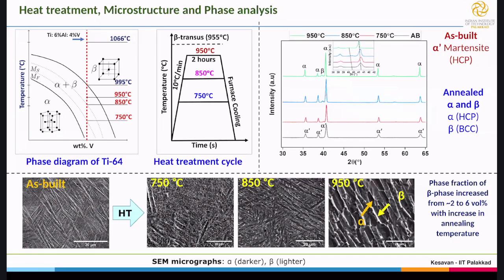So the remedy or mitigation is that I have to take it for heat treatment. Why heat treatment? I need to restore the desirable phases or structures. So I take the material and heat it close to the beta transus temperature, which is almost 955 degrees Celsius, and do furnace cooling. Here we kept it at three different temperatures close to the beta transus, namely 750, 850, and 950 degrees Celsius. As the temperature increases, you can see the alpha and beta separating out, and the size of the laths also increases.